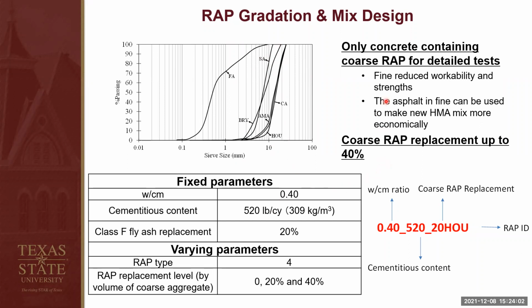The reason why we did not use any fine aggregate was because fine RAP reduces concrete workability and strength significantly, and also the asphalt content in fine RAP is higher than in coarse RAP. So we think those asphalt can be better used in hot mix asphalt, because asphalt is the most valuable component in RAP. So for our mix design, we followed the TxDOT Class P, which is a paving mixture.